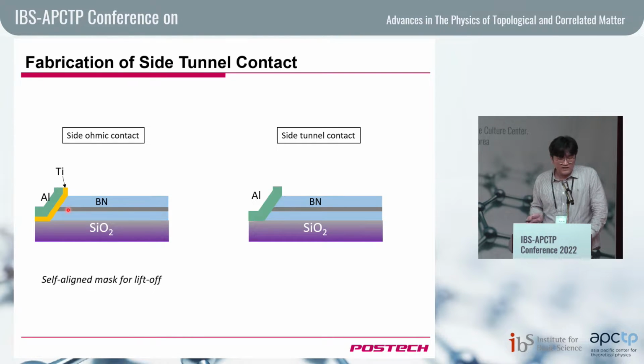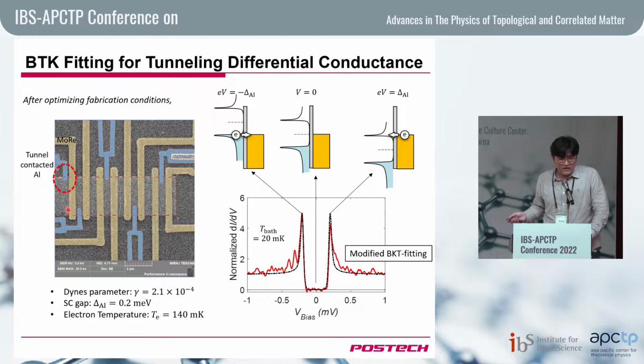then we saw a well-behaving tunneling contact, actually. So this is graphene encapsulated with boron nitride, shaped into a rectangle, and then we put an aluminum side contact directly to the graphene. You can view this as a superconductor, of course, and the graphene as a normal metal. And you expect this kind of tunneling spectrum because it's basically the convolution of the density of states of this material and the density of states of that material.